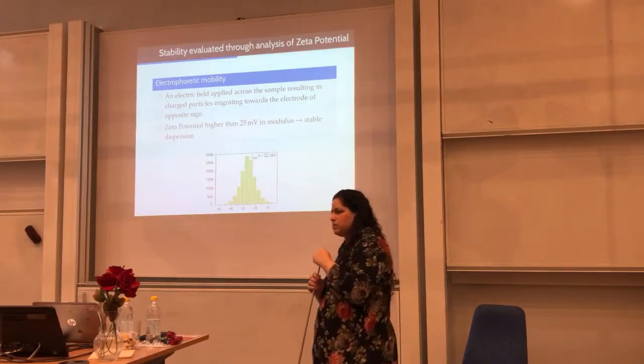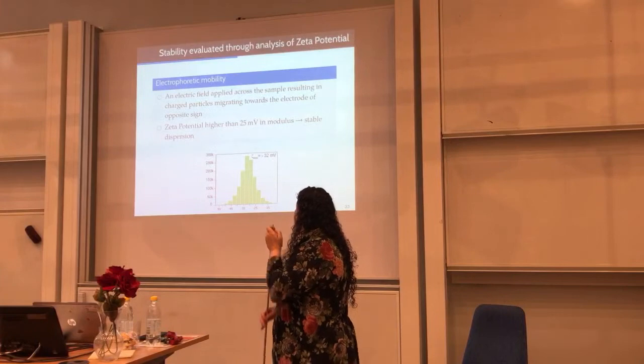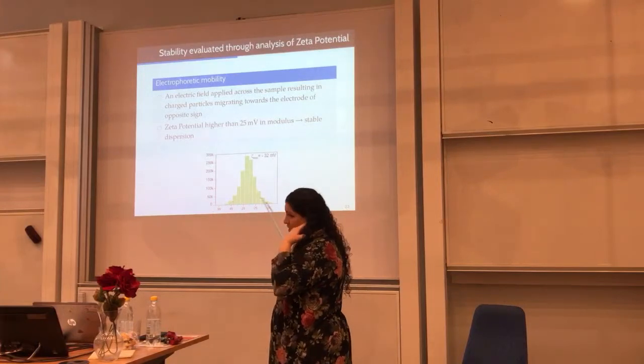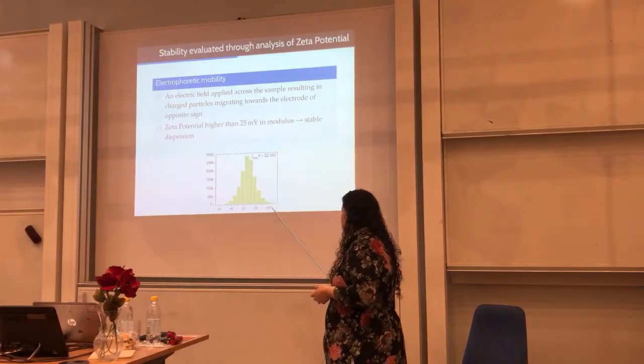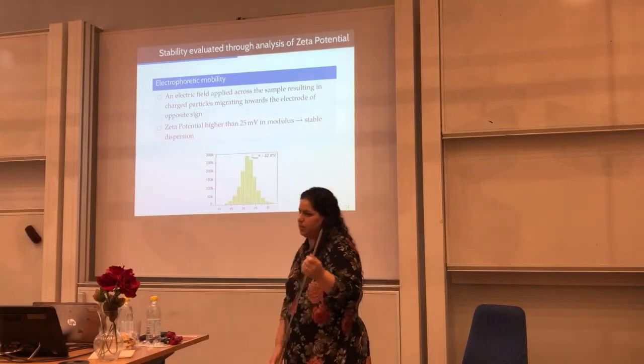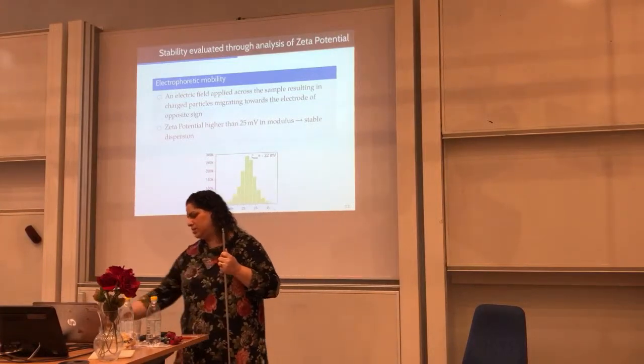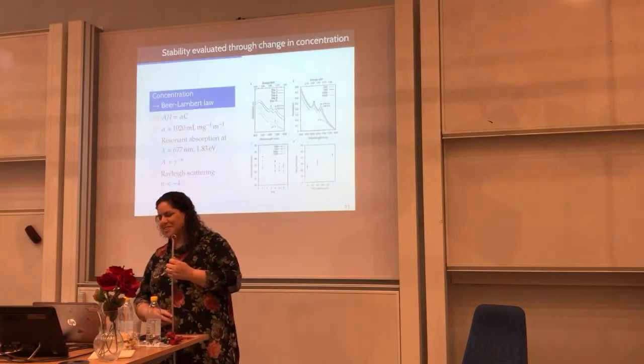So some particles will be dispersed in water, even though some other particles will not be. So you have particles that will be in the range of instability of the zeta potential. So there will be sedimentation. So it didn't solve all the problems.